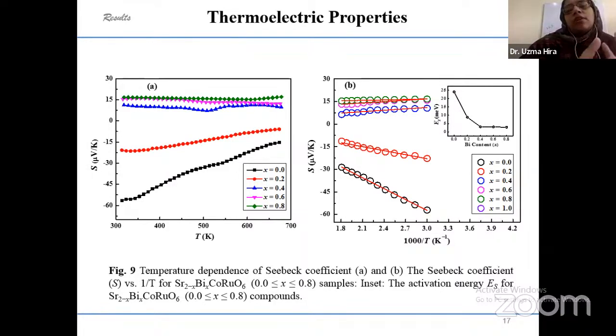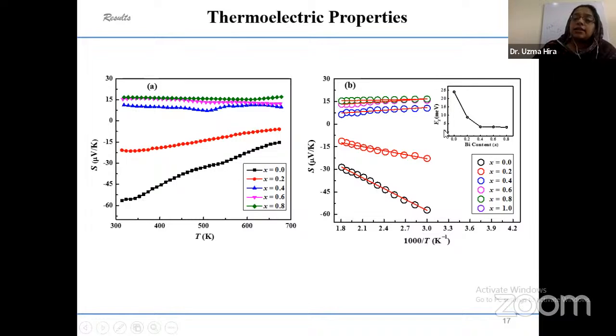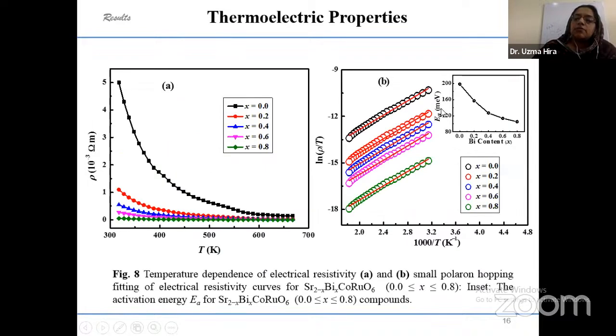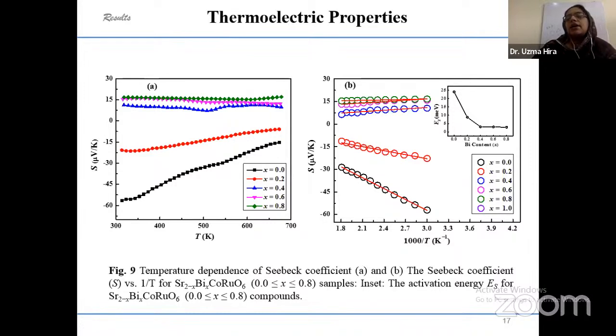And as you can see in our introduction slides, we need both p-type and n-type materials for a thermoelectric module. So with this series of samples, we have both p-type and n-type materials. The small polaron hopping model also fits nicely with the Seebeck coefficient data, and we have also calculated the activation energy from the Seebeck data. You can see the same trend: this activation energy decreases with increasing bismuth dopant. We also obtained activation energy values that are smaller from Seebeck data than the activation energy calculated from electrical resistivity data.